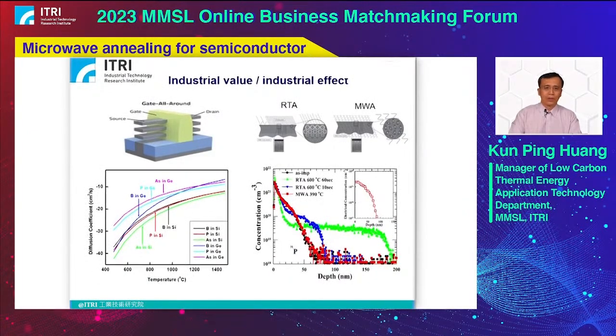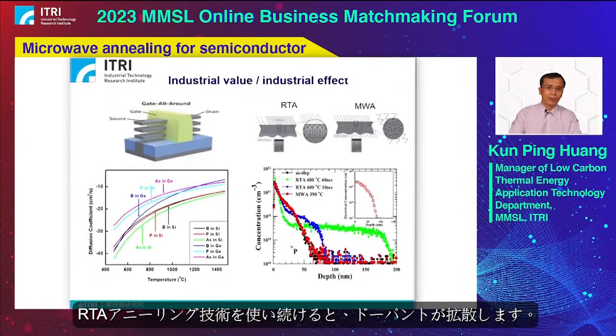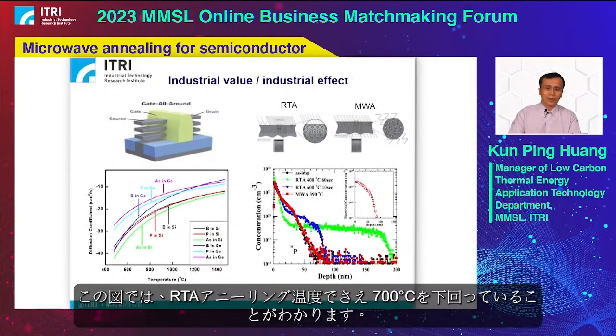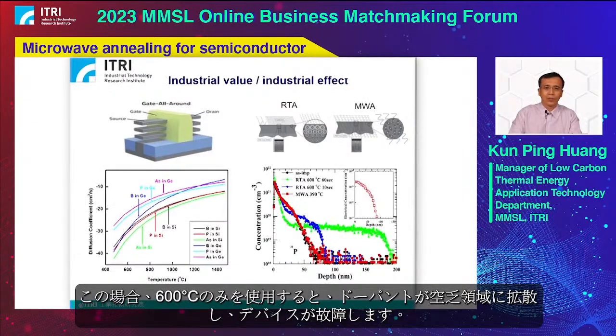So if we continue to use RTA annealing technology, it will cause dopant diffusion. In the figure, we can see that even if the RTA annealing temperature is below 700 degrees C, in this case we only use 600 degrees, it will make the dopant diffuse into the depletion area, which will make the device fail.